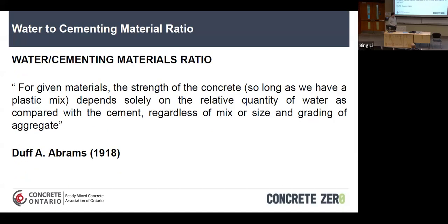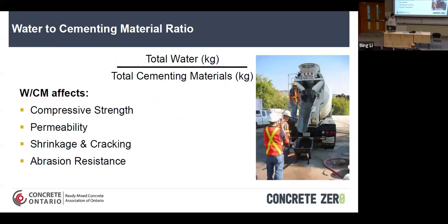Water cement ratio is what impacts your concrete strength. As long as you have good aggregates, it's pretty much the key function for a lot of things in concrete. For example, it impacts your compressive strength, your permeability, and your shrinkage and cracking. And again, this one's like the three bears. If you have a low water cement ratio at around 0.32, then you're gonna get something called autogenous shrinkage. If you get something like 0.8 water cement ratio, you're gonna get drying shrinkage in your concrete. Those are gonna be the major shrinkage factors.